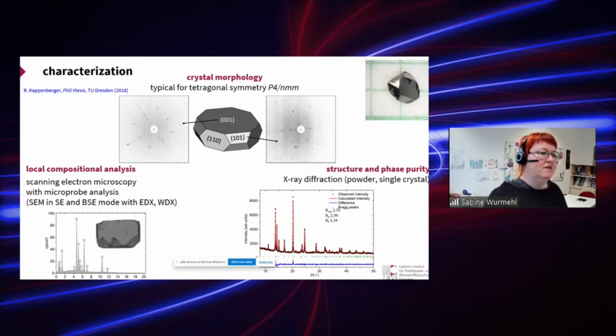We did a compositional analysis using scanning electron microscopy, both in secondary electron and backscattered electron mode, revealing chemical homogeneity. We also did EDX spectroscopy to really probe that we are dealing with a lanthanum oxygen iron arsenide material. We also did X-ray diffraction on powders using both crushed single crystals as powder, but also single crystal diffractometry.